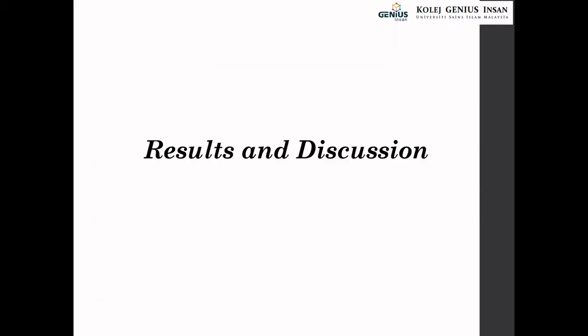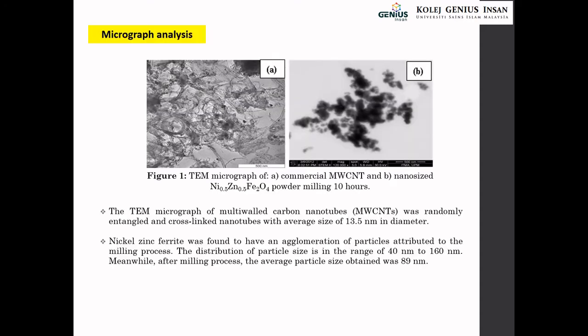Results and discussion. Micrograph analysis. This is a TEM micrograph of multi-wall carbon nanotubes, which were randomly entangled and cross-linked, with an average size of 13.5 nanometer. And this is the nickel zinc ferrite. It was found to have an agglomeration of particles attributed to the milling process, and the distribution of particle size is in the range of 40 nanometer to 160 nanometer. However, after the milling process, the average particle size obtained was 89 nanometer.